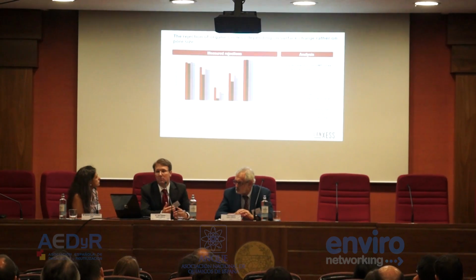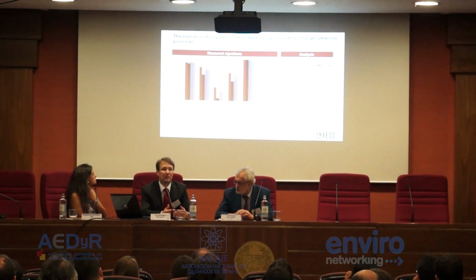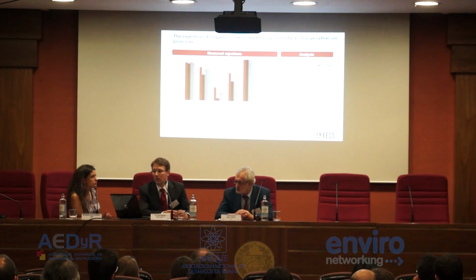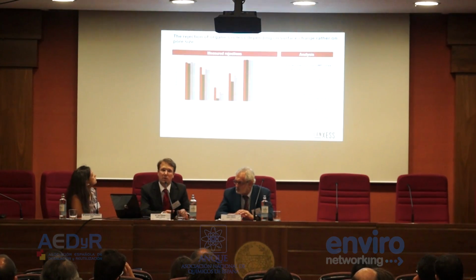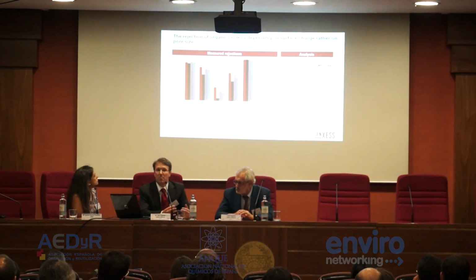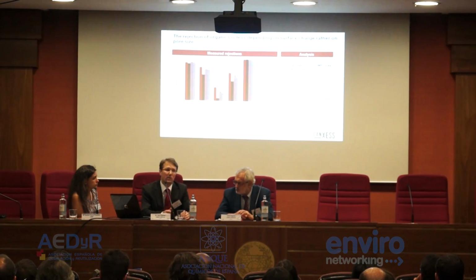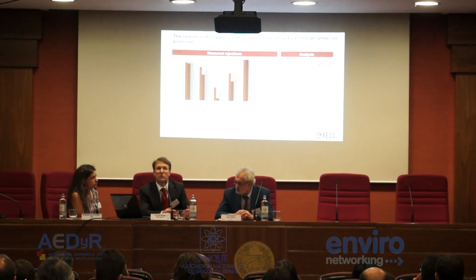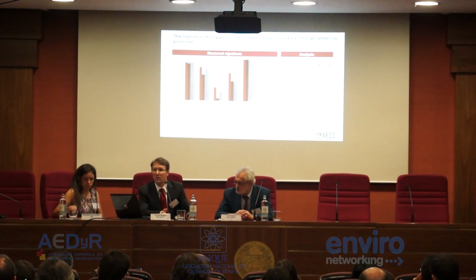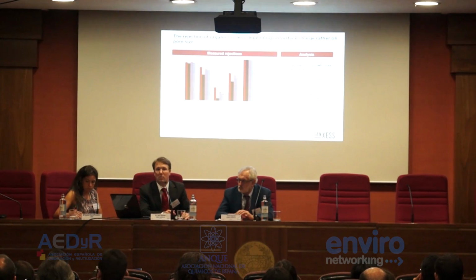We were a little bit surprised by the result because isopropyl alcohol is not a very big molecule, and we were surprised that this rejection was so high. So we made a comparison of different models. One was the model of the volume of the molecule, the other one was a dipole model, and finally the best fit was actually a mixture of both models. So of course the size and the structure of the molecule has an influence on the rejection, but also the dipole moment of the molecule.